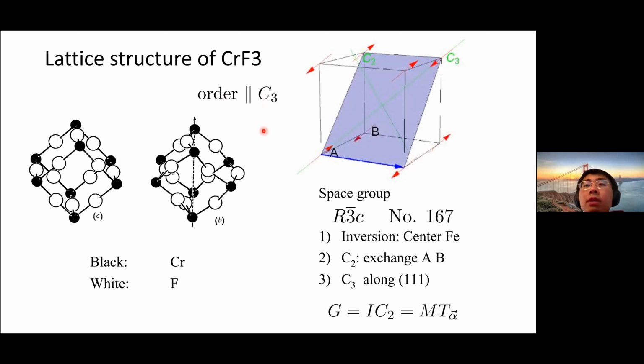So in this case, I first want to have a quick review of the crystal structure of this material. If you look at the crystal structure, this is not a perfect cubic structure. You can see that chromium trifluoride is a distorted cubic structure, where these atoms are distorted from the ideal position in the cubic case.